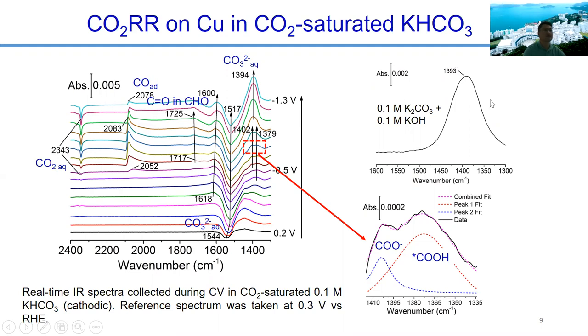This is confirmed if you measure the wavenumber of carbonate in potassium hydroxide solution, you can see it's actually the same number. So those are the very important bands. Let's look at some of the bands that are much weaker. This one is about 2078. This band is associated with the adsorption of carbon monoxide. And there's a very weak band about 1700.